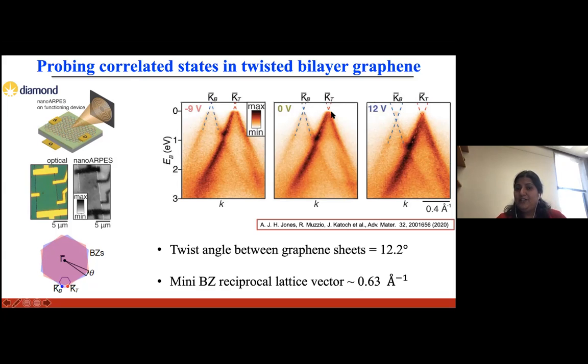at low binding energy. And these cones look like they start to hybridize around 1 eV. And here we see that the Dirac cone of the bottom layer is less intense, and this is because of the attenuation of the photoelectrons through the top layer.